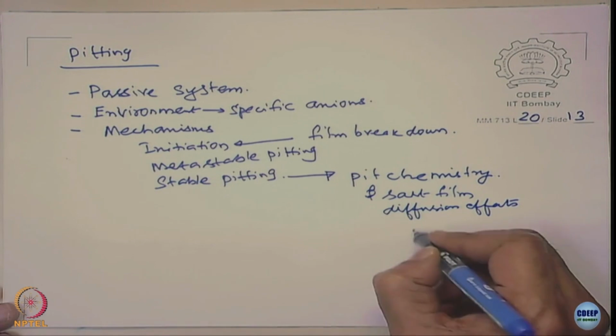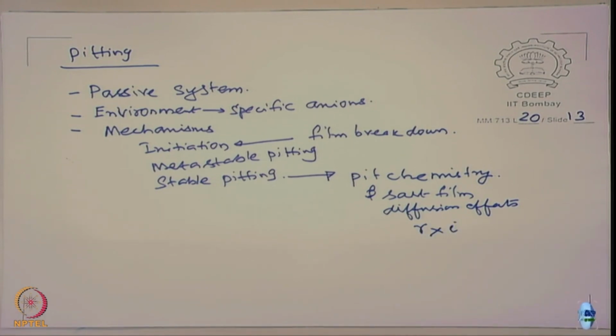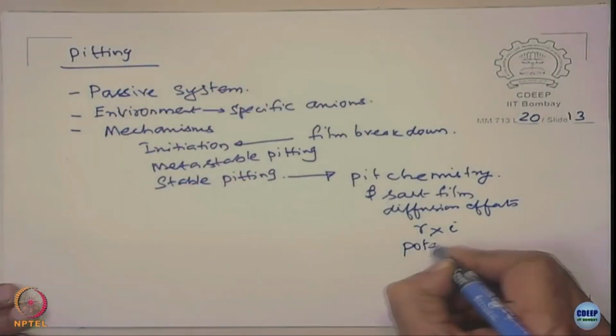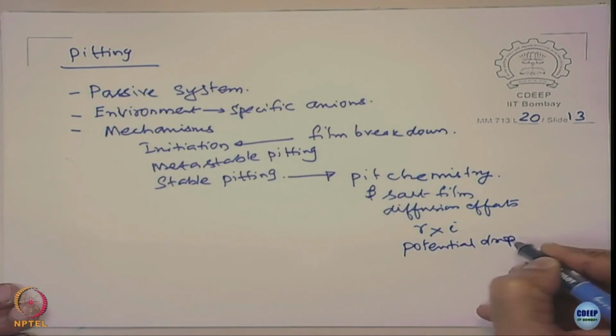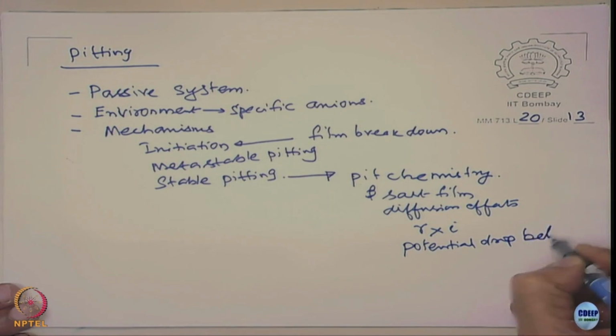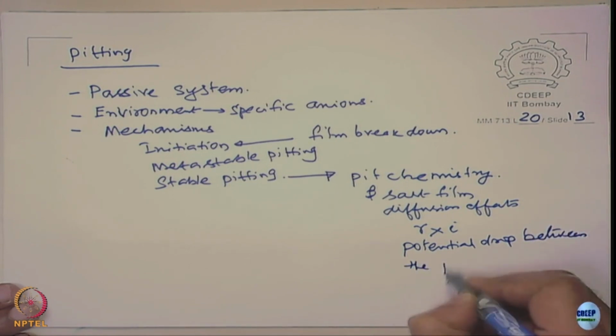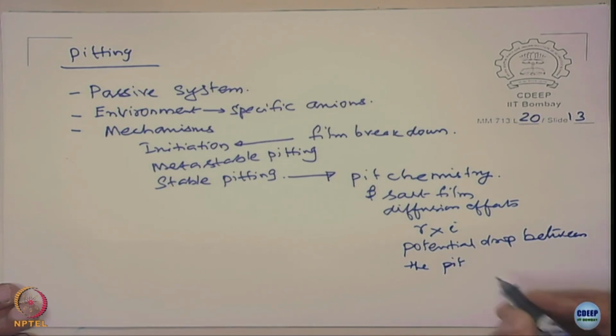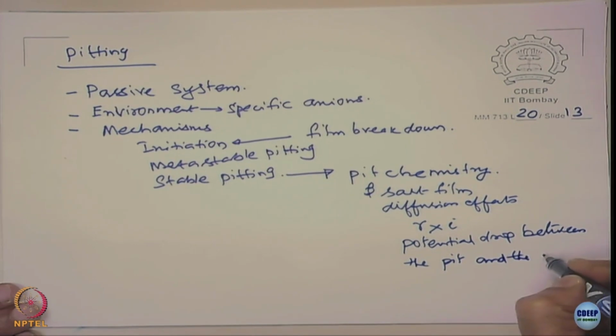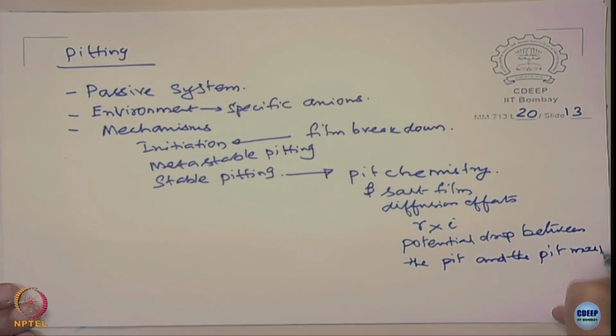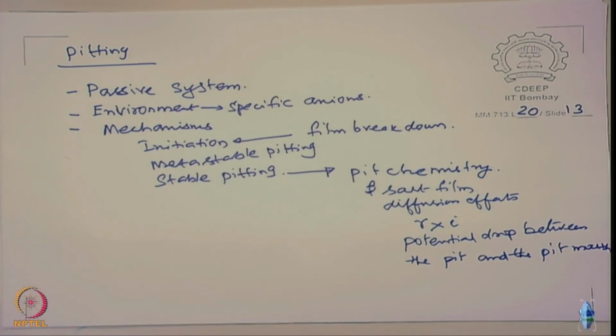We also had a criteria called the IR criteria we talked about, right. It also depends upon the potential drop between what? Between the pit and the pit mouth. Because there is a potential drop, the growing pit, that front, does not allow repassivation, right. They are kept at much more negative potentials, and the dissolution occurs. We talked about the mechanisms.